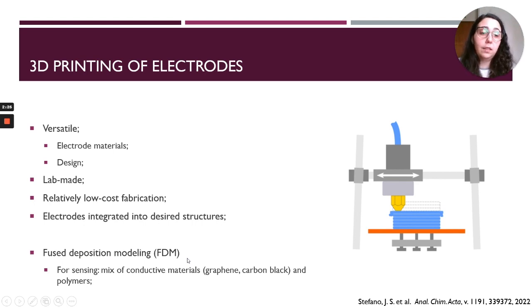The most used technique for 3D printing electrodes is called fused deposition modeling, and it is the technique that is most used for 3D printing in general, in which you have a filament that is heated and then deposited by a nozzle. And this is done in a layer by layer fashion. So when the first layer cools down, it hardens, and you can add the next layer on top. And then you can print the device you wish in 3D. Specifically for sensing, we usually use a mix of conductive materials, usually graphene or carbon black, and some polymers as the filament. So you still have good mechanical properties, filaments that are adequate for 3D printing, and you have conductive materials.